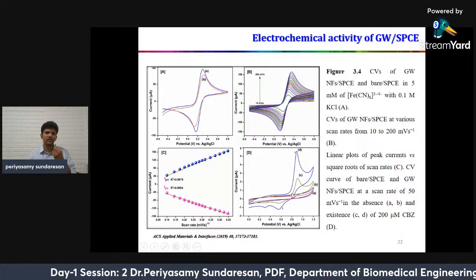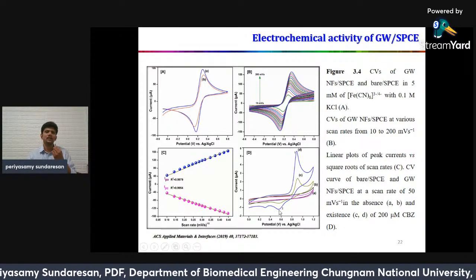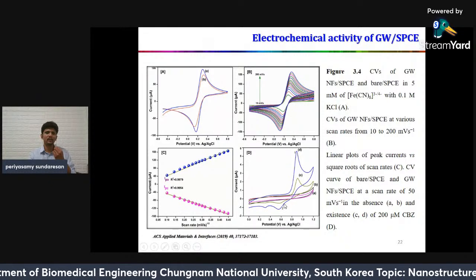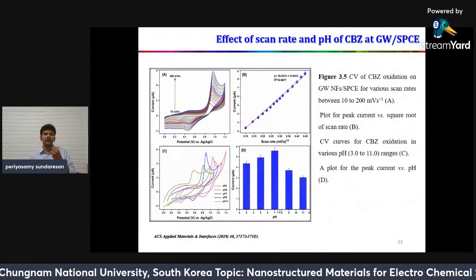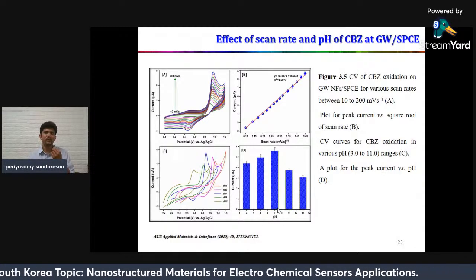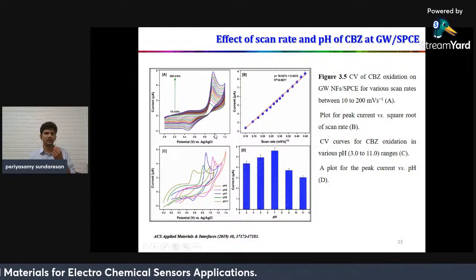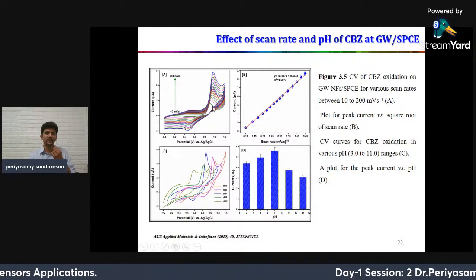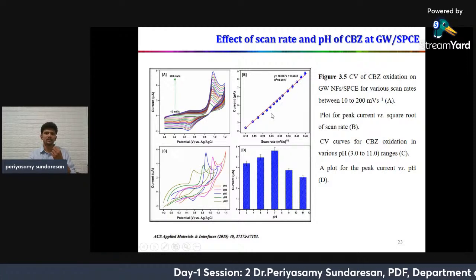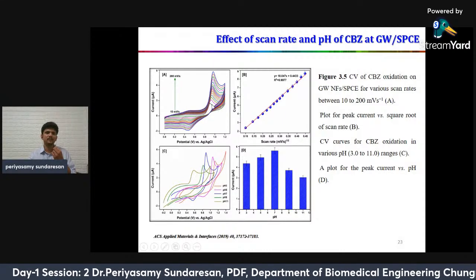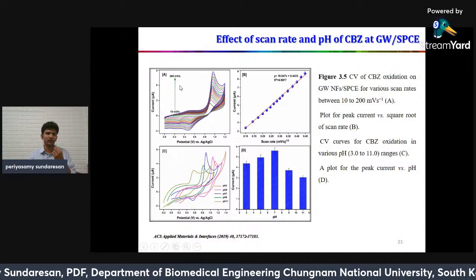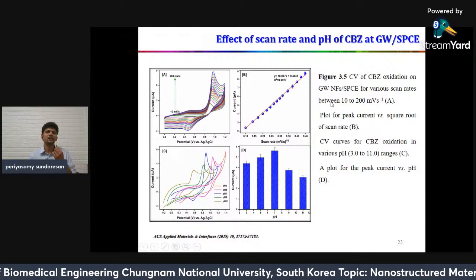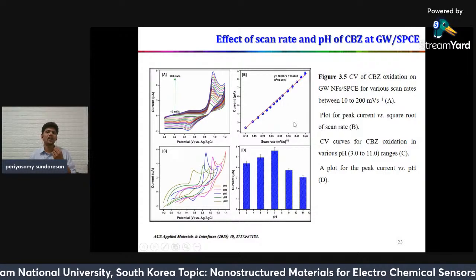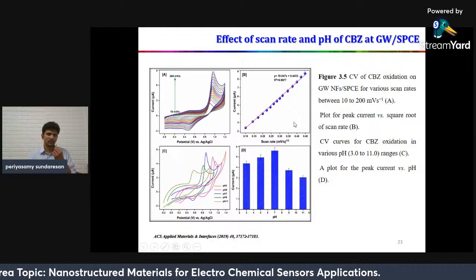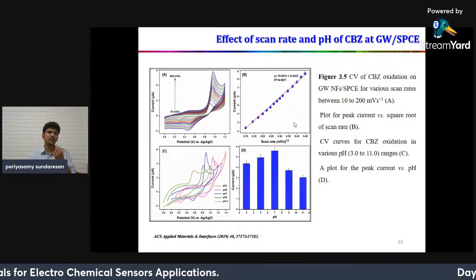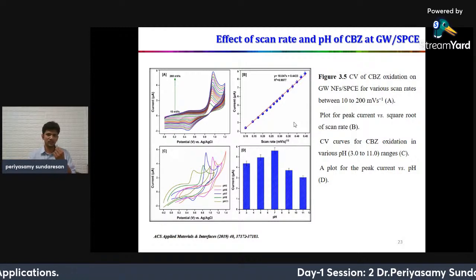I get two peaks at 0.82 volt and 0.6 volt. This is the major oxidation peak, and this is the reduction peak. The effect of scan rate and pH of the carbendazim is very important for the electrochemical sensor studies. That's why I studied various scan rates and pH. Here, the scan rate is increased linearly. They don't have any disturbance. The peak current increases linearly from 10 to 200 millivolts per second. That's why it is an adsorption controlled process. It means the reaction is only on the surface. The analyte and the material react only at the surface, not by a diffusion controlled process.